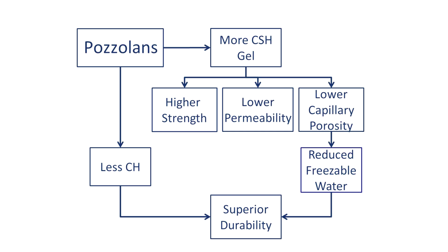So here's sort of a flow chart. The source I got this from was talking about using specifically silica fume to make more durable roads or exterior concrete that's subjected to freeze and thaw. But if you look at it in a general sense for pozzolans, this still holds true. When we add pozzolans to our concrete, we consume the calcium hydroxide, so there's less of it. That creates more calcium silicate hydrate gel that gives us higher strength and helps plug the pores. There's less open space. Calcium hydroxide is a big crystal that's very soluble in water. So once it dissolves, it leaves a big void behind, and that mineral salt, if you will, leaches to the surface and forms part of what you see as efflorescence.